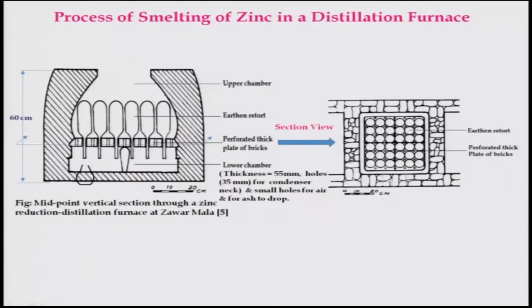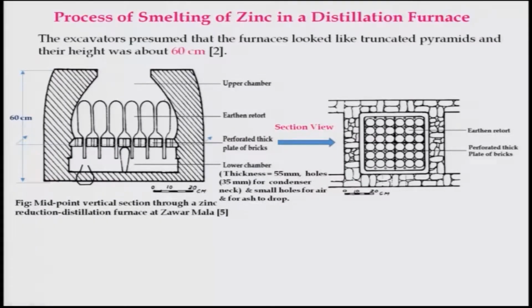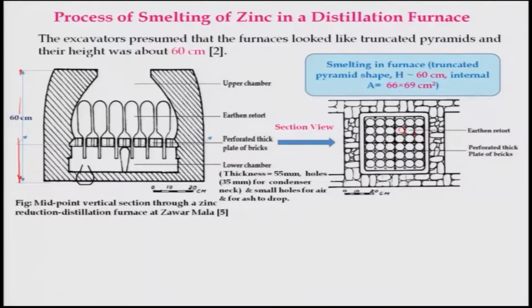So, this is the vertical section of a zinc reduction distillation furnace, which was obtained at Zawar Mala, and if you look at it, it is basically a truncated pyramid shape, and this height is 60 centimeters. If you look at this, from here to this is 60 centimeters, and these are the earthen retorts which are placed in this, and this is the sectional view. It will be shown here, this perforated thick plate of bricks, which will be holding these earthen retorts, and these are the small holes for the air to pass through.